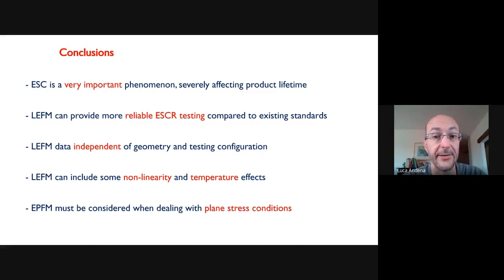While fracture mechanics, even the most simple linear elastic fracture mechanics, can provide a good answer to this, because it can provide data which is independent of the geometry and of the testing configuration. And with some attention, you can also include some nonlinearity effects, adopting a sort of pseudo-elastic approach by considering the proper values of the strain and time for the modulus. You can also consider the effect of temperature, which you can use freely to accelerate testing, whenever needed.